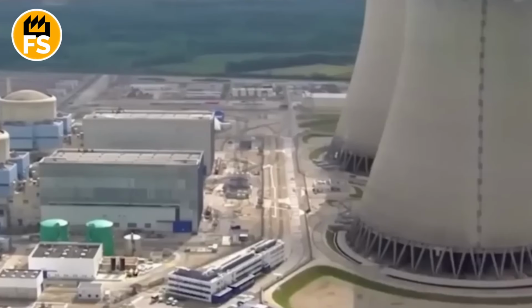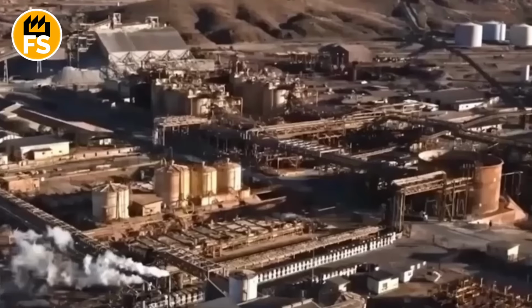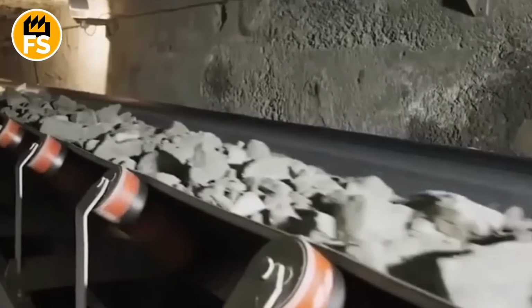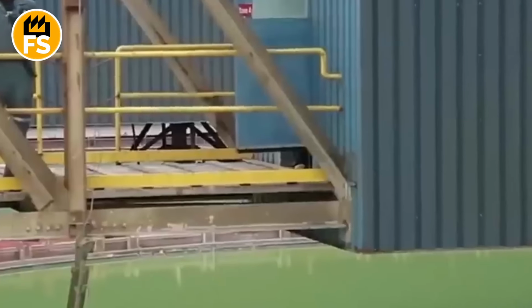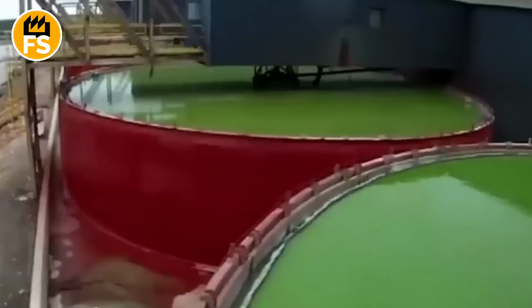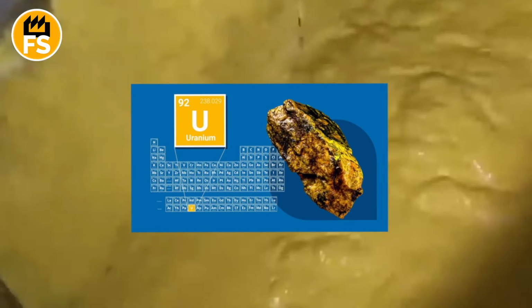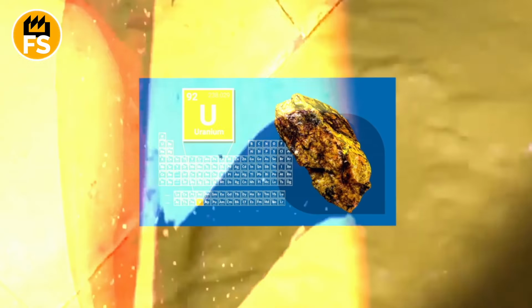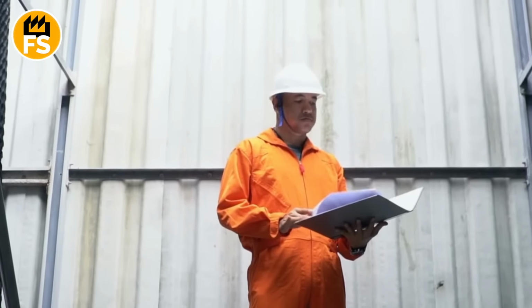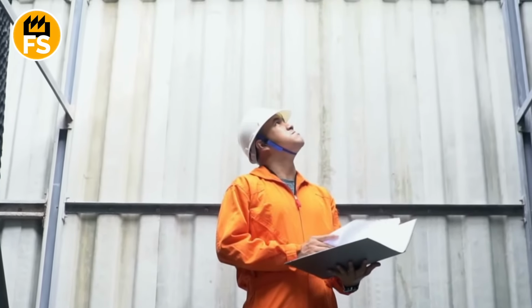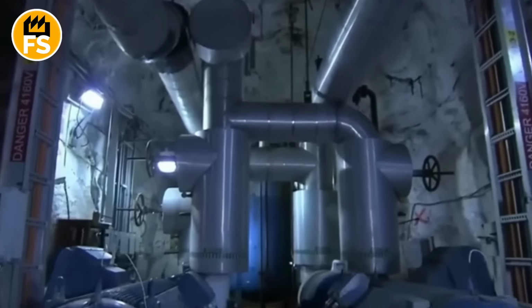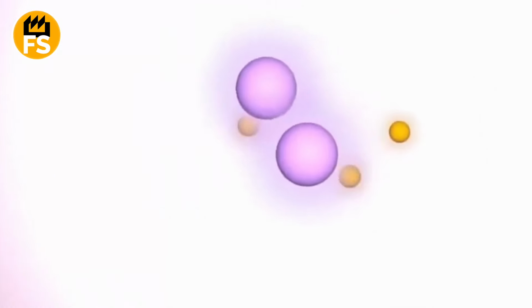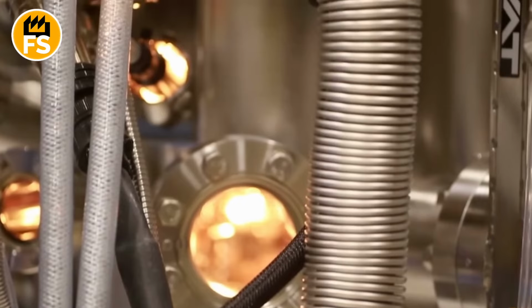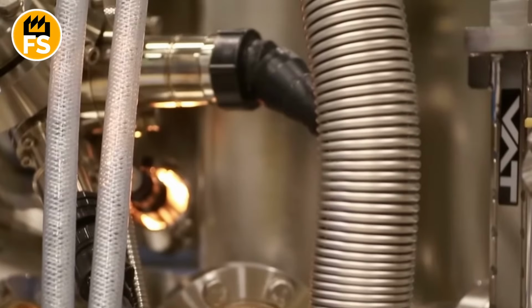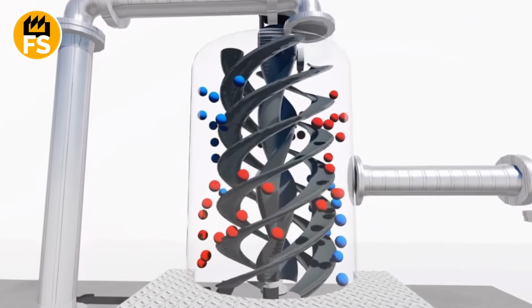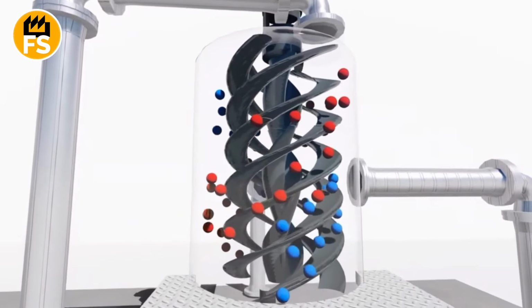As a result, we get two things. On one hand, tons of wet, now unnecessary sand, so-called tailings, which are toxic waste, and on the other, a murky, greenish-yellow liquid containing our precious uranium. This liquid needs to be cleaned and concentrated. It is passed through a series of columns filled with special ion exchange resins. Imagine this as a high-tech water filter. The resins, like a magnet, pull out only the uranium ions from the solution, letting everything else pass by.